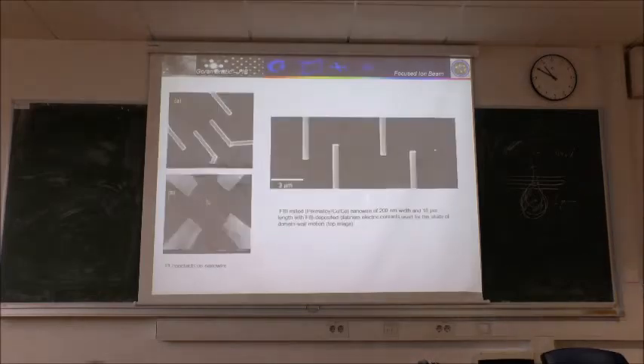Example of the deposition. Here is just one more schematic. First we adsorb the gas molecules, which contain some platinum, iron, gold, tungsten, and so on, and some organic radicals around. They are in the gas form. Using focused ions or even electrons, we decompose this material, and the tungsten, platinum, or gold remains at the top of our sample, and those species that are volatile and made due to this decomposition just go into the vacuum system.